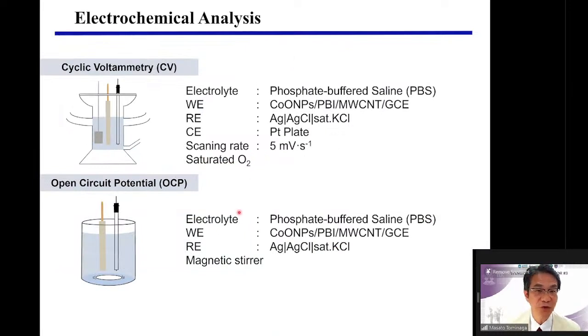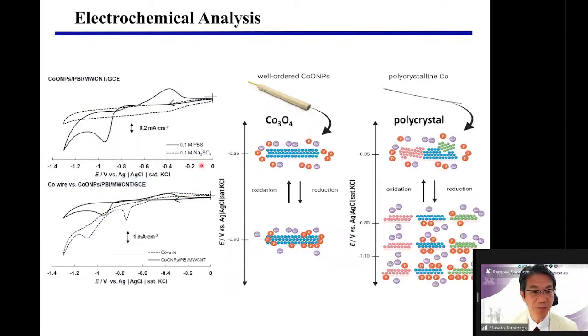Okay, I move to the electrochemical method. I use cyclic voltammetry and open circuit potential. So this is cyclic voltammetry when I use the cobalt oxide nanoparticle modified electrode. When there is no phosphate ion, I cannot detect any redox reaction of phosphate like this one. And if phosphate ion is present in the solution, I can observe this peak due to phosphate ion.